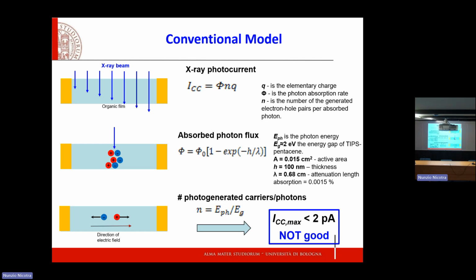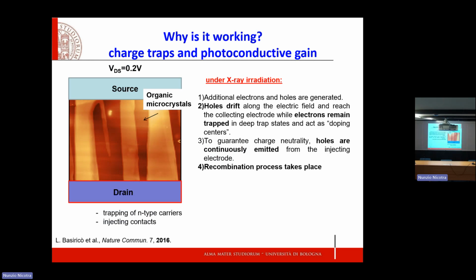And honestly, it took us a few years to feel confident to believe that what we were looking at was not an artifact, because we were saying we're just measuring some systematic effect. There's an error in the measurement. We're not really collecting anything because we shouldn't be collecting anything. Now, that was until we realized that what was going on was the activation of a photoconductive gain effect, which is basically produced by the trapping of one of the two carriers, electrons in this case, that are generated by each impinging photon.